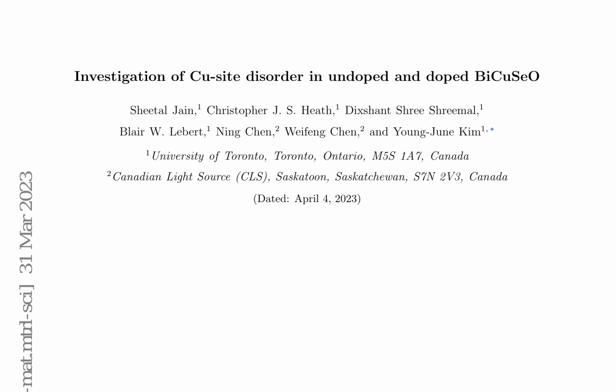The main findings from the X-ray diffraction and EXAFS studies are the unusually large UISO parameters for Cu in undoped BiCuSeO and large sigma-squared parameters for both Ag and Cu in doped BiCuSeO samples. These thermal displacement parameters are independent of doping concentrations and temperature at low temperatures. The possible origin of the observed large thermal parameters and their implications for thermoelectric properties of doped and undoped BiCuSeO are discussed.